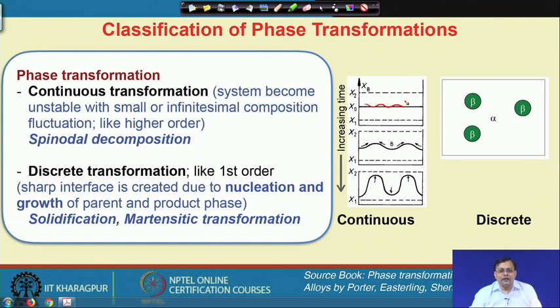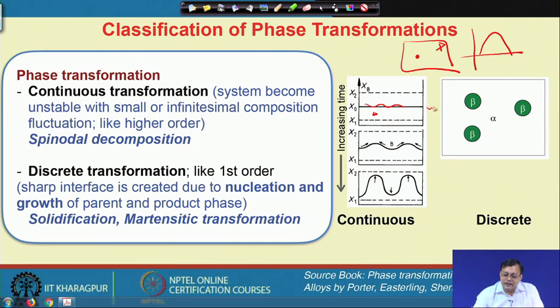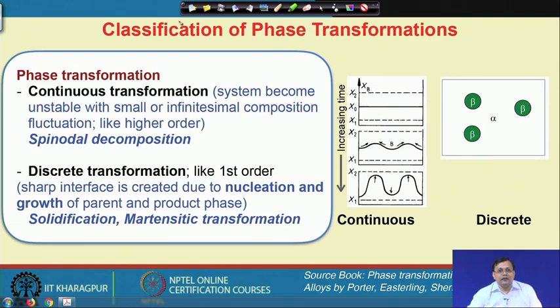It also says in other words that there is no activation energy for such a process. Because for making any nuclei of a second phase particle, if I have a parent phase and I want to introduce a product phase into it, then there will be an activation energy barrier, which is controlled by the surface area, the volume, and so on. But in this case, a very small composition fluctuation always makes the system unstable, because there is a net decrease of the free energy of the system. And so, spinodal decomposition is a type of continuous transformation.